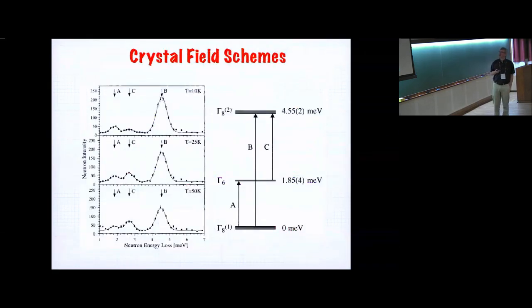But they're all there. And this is another one that we don't do very well, I would say, today, but we did excellent jobs at it 20, 30 years ago, in crystal field analysis. And with many of these rare earth pyrochlores, but also other rare earth quantum magnets, this becomes more important. It's actually the crystal field scheme that we often then say this is a quasi-spin half system. It's because of the actual way that these levels break up that we can imagine the ground state as a spin half system rather than what holmium really is, for instance.